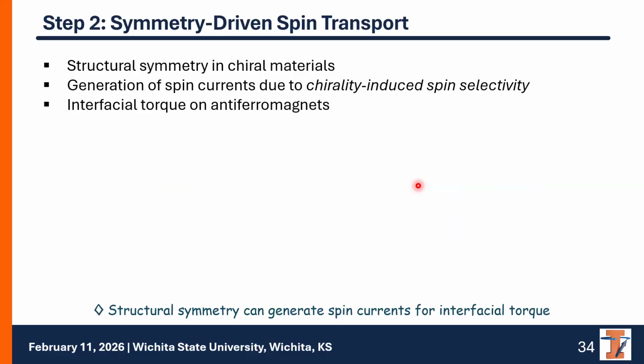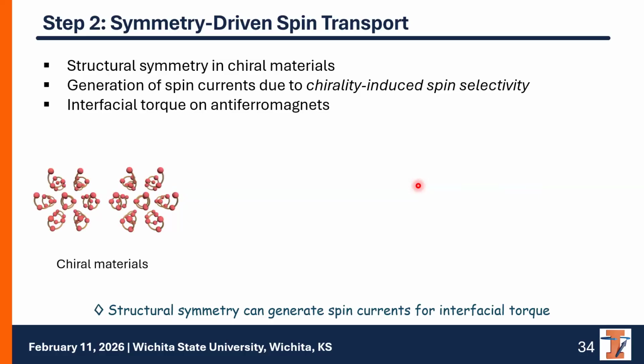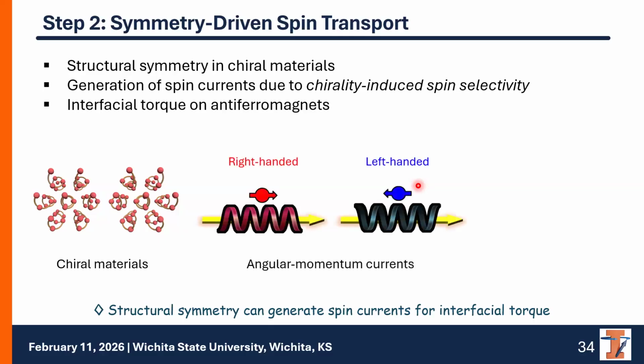The second step is to transport spin angular momentum in antiferromagnets using structural symmetry. In this case, I want to use chiral materials, which have a chiral molecular or atomic structure. In these chiral materials, the spin angular momentum of the electric current can be polarized parallel or antiparallel to the current direction. And this spin information is determined by the structure, right-handedness or left-handedness.